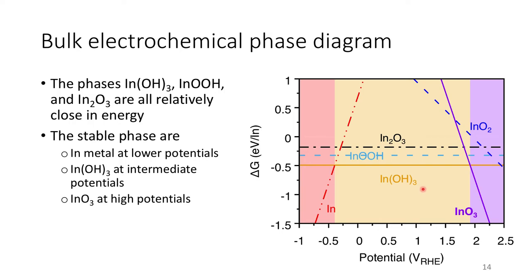Nonetheless, on the surface, it may be possible for indium to exist in the 3+ oxidation state, but be present in a different phase. For instance, the InO2 phase could be present since the platinum surface can actually pull electron density from the oxygen atoms in InO2 and allow indium to stay 3+.